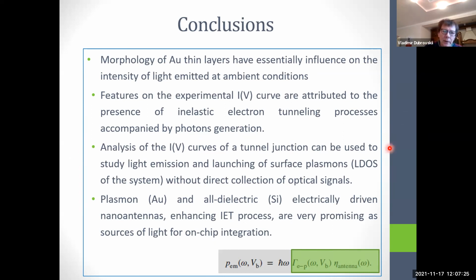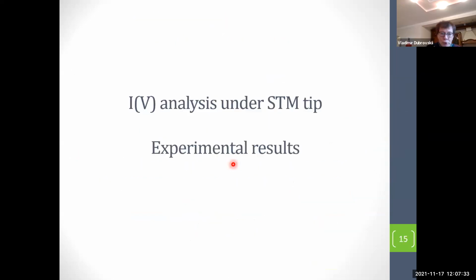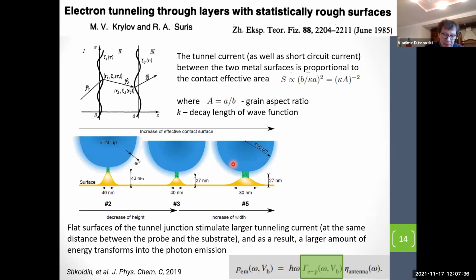I have a question regarding the morphology of the gold film. You mentioned the gold film is made of merged, coalesced grains. Why is it so? Is it because it starts with three-dimensional islands at the beginning, or what is the reason? Because of course, on some substrates we can have more or less flat gold layers without any grains. It's directly correlated to the method of thermal evaporation which we have used to fabricate this substrate.